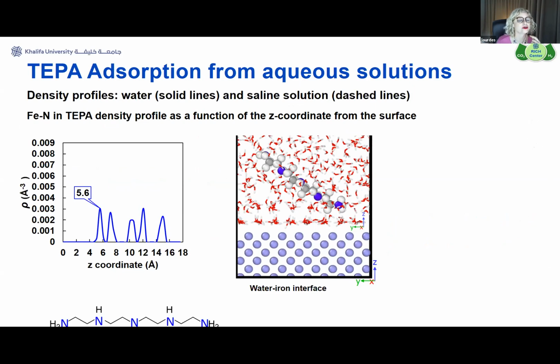So here I'm showing the density profile and the conformation of the TEPA molecule when we have just water, okay? And here we can see that the TEPA also tries to get in contact with the surface. However, the water double layer forces it to be farther away from the surface than when we didn't have water.